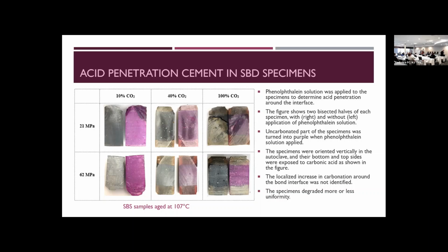By looking at this, we kept the orientation of all these samples, as you see in this figure here. And we could not really localize an increase in carbonation around the bond interface for our system. So the carbonation basically happens pretty uniformly in the sample, if you want to take it as such. This might have some implication for the role of CO2 in the bonding process.